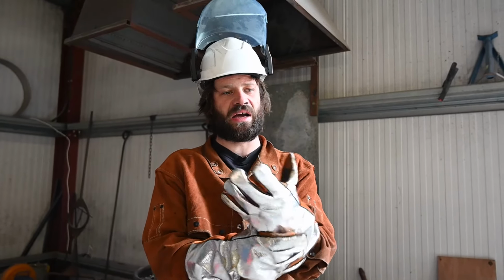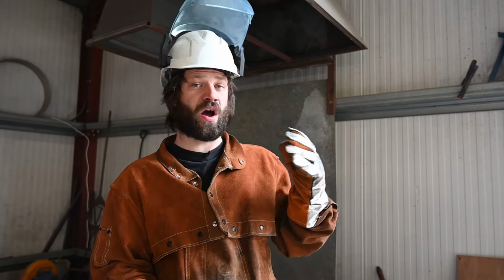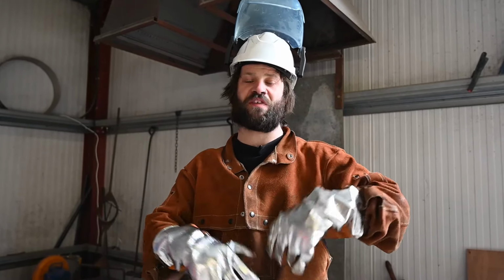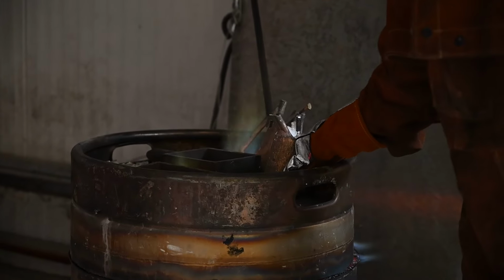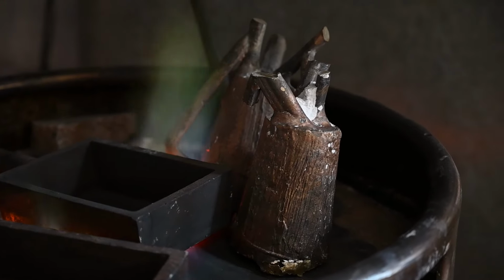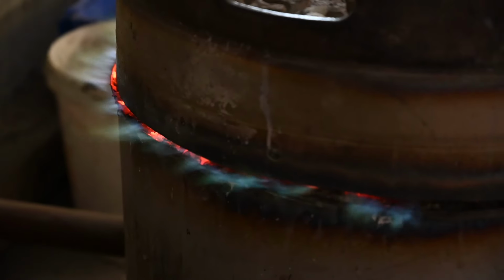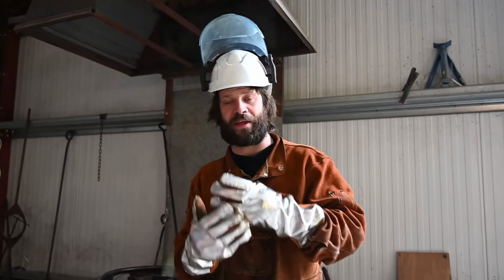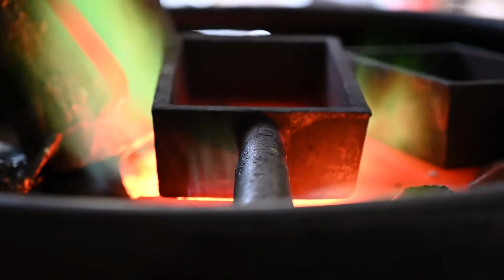If you're ever pouring bronze, never put cold ingots into the furnace, especially when the bronze is molten, because if you put a damp or cold ingot into the furnace, the moisture in the bronze kind of explodes. So if you ever put bronze into the furnace, make sure it's preheated and all the moisture is evaporated out of the metal. So we'll pop these cups on top, then all the moisture evaporates, and once they're nice and toasty, you pop them in the furnace, and they can melt down with the rest of the bronze in the crucible.